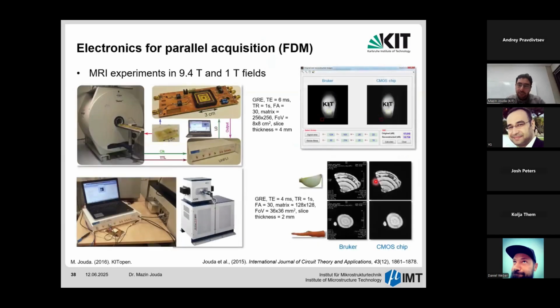And after that, we tested the chip in MRI experiments in a high field, preclinical imaging system of 9.4 Tesla magnets, in a gradient echo imaging experiment. And this is the image from the chip compared to the image from the Bruker. We see that it's capable of acquiring the signals faithfully, even though the noise performance is not as great as the commercial system. We have a drop in the SNR by around 3 dB.